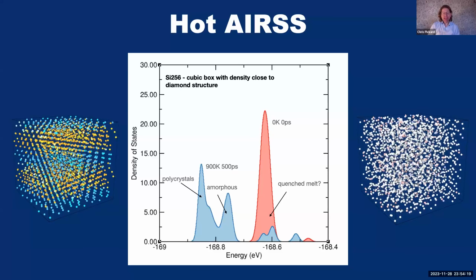But now if we do an anneal, in this case, 900 Kelvin for 500 picoseconds, many thousands of times, we can actually get a density of states of annealed structures. And interestingly, we see remnants of the quenched melt peak. We also see a separate peak, which looks like clearly amorphous phases. But then at low energies, we see yet another peak, which are the crystalline phases, or in fact, polycrystalline, because in this shaped unit cell, there's no single phase crystal that would fit in.